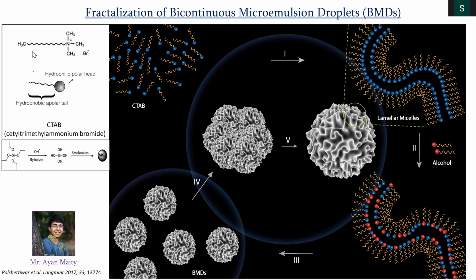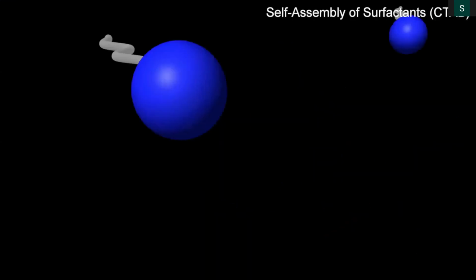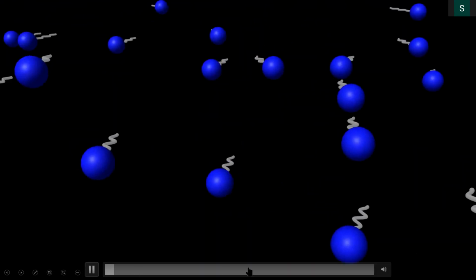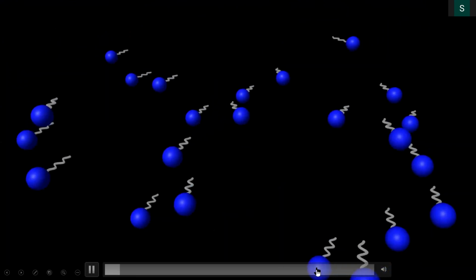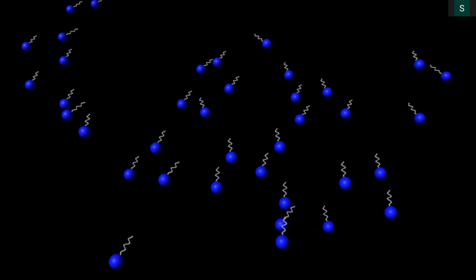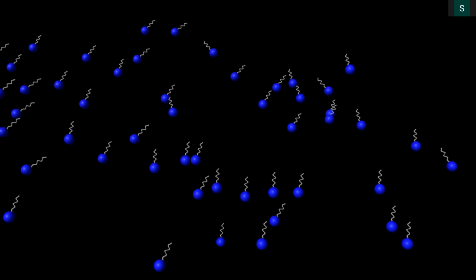So you have this polar head and hydrophobic tail. These are the surfactant molecules. And we know whenever we add the surfactant molecule in the solution, in the solvent, they try to form the micelles, reverse micelles, standard micelles, or sometimes lamellar phases. You see, they were self-assembled to form such a lamellar phases. And I will show you the animation for a more clear version. So these are the template molecules, polar head, non-polar tail. We added them into a solvent. Here it's the water and xylene mixture, and